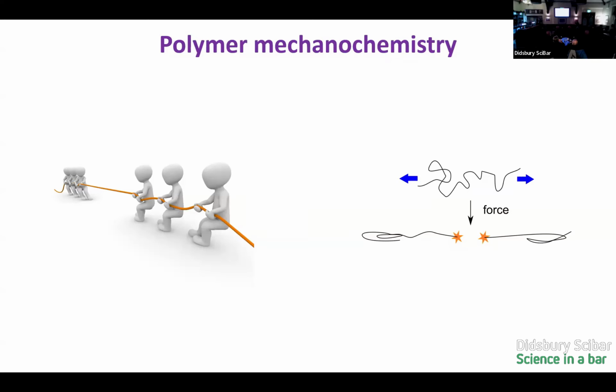And that's not great, because in reality, what we want from the polymer is its long chain nature. We want it to coil and form these kind of strong structures where we have these entanglements. If we all of a sudden pull on these chains and we break them, our polymer is now half the length it used to be, and then it's almost half as useful, right? So we've reduced our molecular weight by half, and we really don't want that.